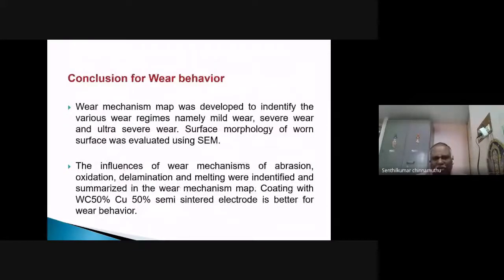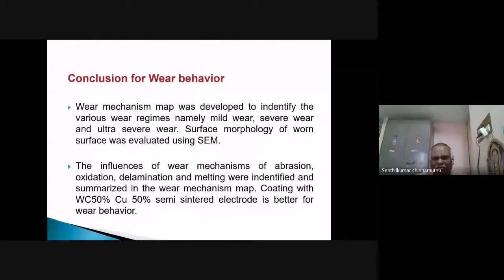Conclusion from the wear behavior. A wear mechanism map was developed to identify the various regimes called mild wear, severe wear, and ultra severe wear, and we have to identify which region is the safest, which load and which sliding speed is the safest. The surface morphology of the worn surface was evaluated using SEM, and the influence of the wear mechanisms of abrasion, oxidation, delamination, and melting were identified and summarized in the wear mechanism map. Coating with the 50% tungsten carbide, 50% copper semi-sintered electrode is better for wear behavior and increases the wear resistance compared to the sintered electrode.